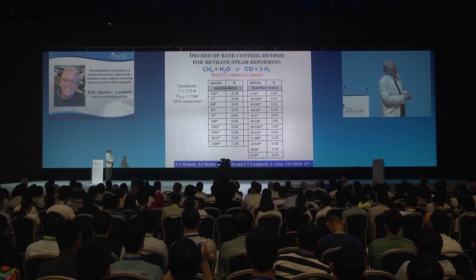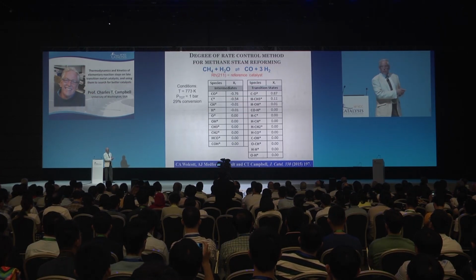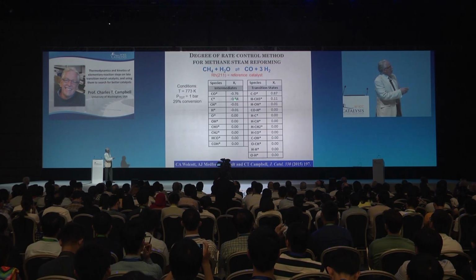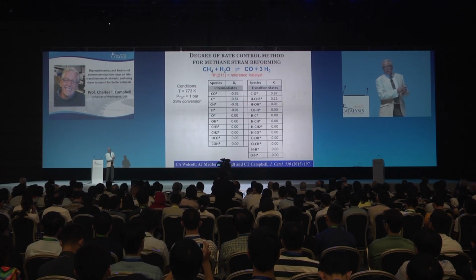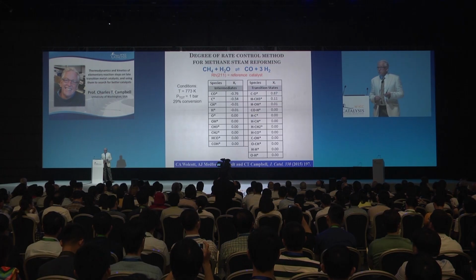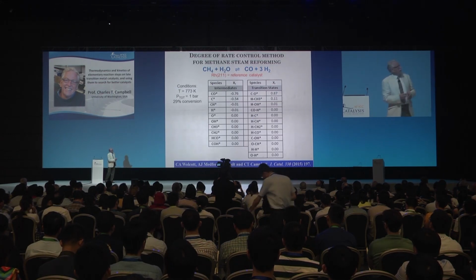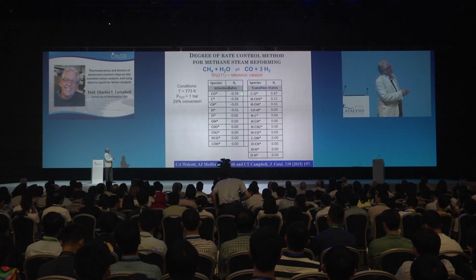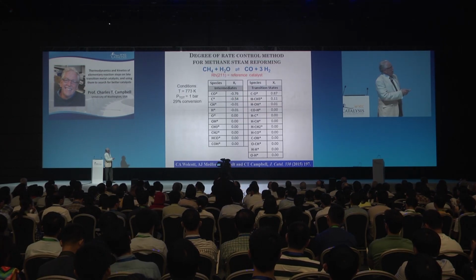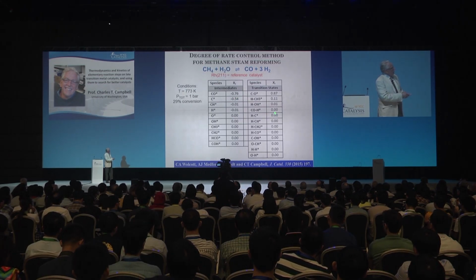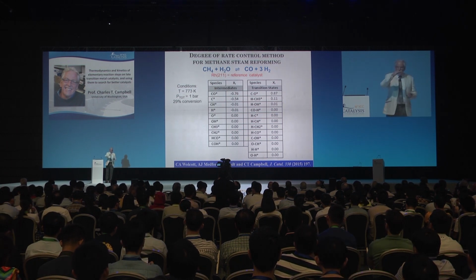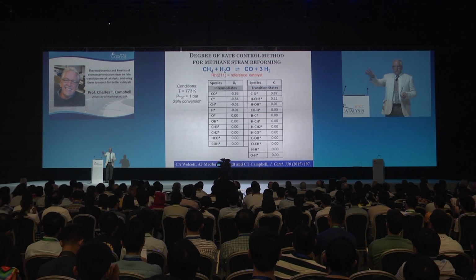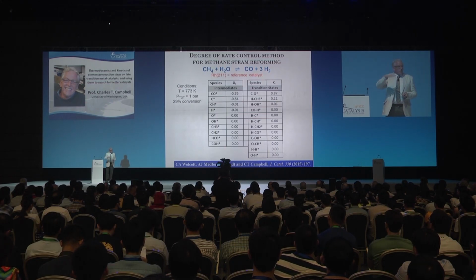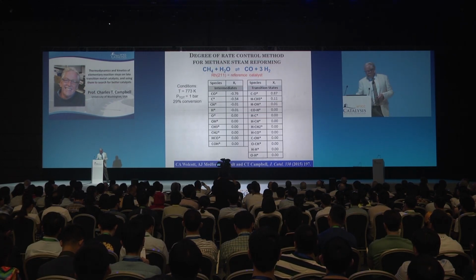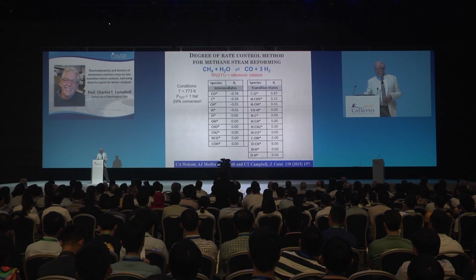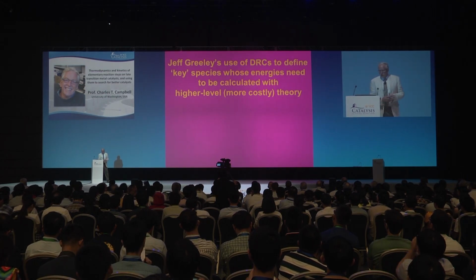And for the adsorbed intermediates, the degree of rate control is essentially 0 for everything except for these 2 adsorbed intermediates that have negative degrees of rate control. That is, if you stabilize those species, then you slow the reaction rate down. And so all these zeros mean that if you change the energy of that species, it doesn't affect the reaction rate at all, at least for small changes in the energies of those species. And so it teaches you how to think about many aspects of the kinetics of reactions